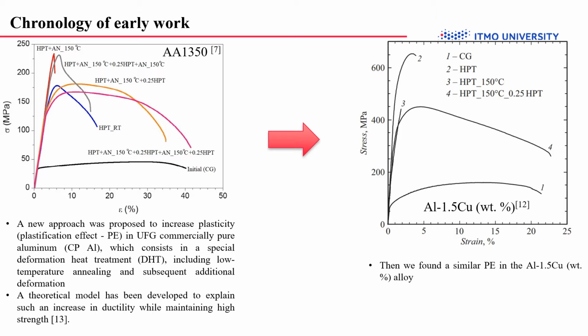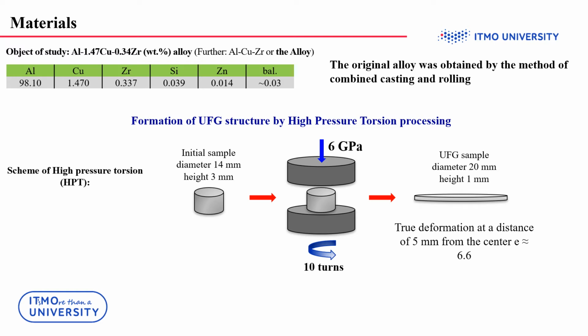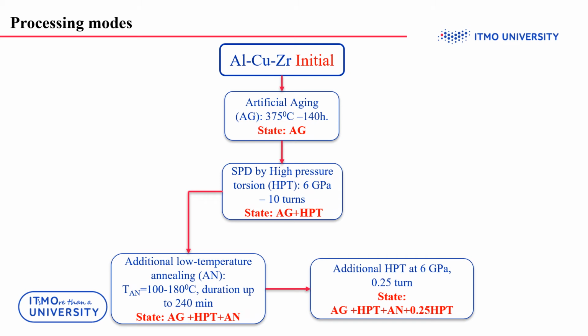Zirconium was introduced to form metastable precipitates of the Al3Zr phase to provide the thermal stability of the mechanical properties of the alloy at elevated temperatures. The chemical composition of the studied aluminium-copper-zirconium alloy, for simplicity we'll call it just alloy, the method of its obtaining in the initial coarse-grained state, as well as the scheme and parameters of UFG structuring using the HPT method are shown here. The initial coarse-grained state was obtained by the method of combined casting and rolling.